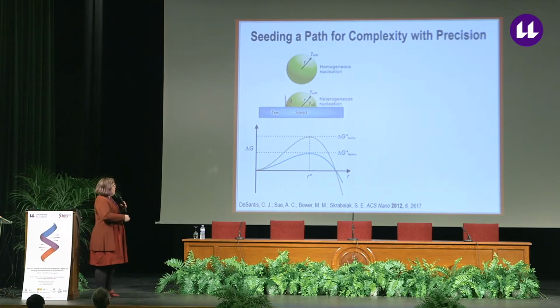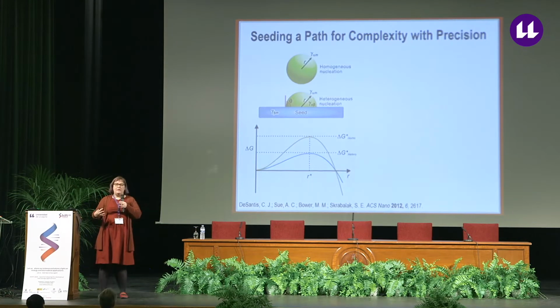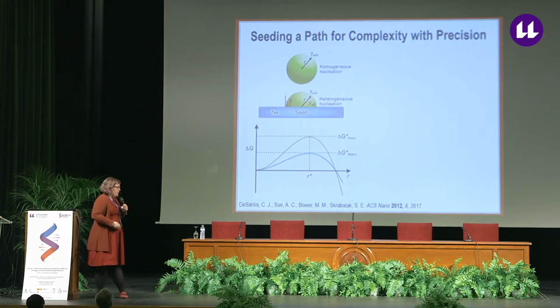And this seems like a reasonable starting point because the barrier for heterogeneous nucleation or seeded nucleation is lower than that of homogeneous nucleation or free nucleation in the solution phase.